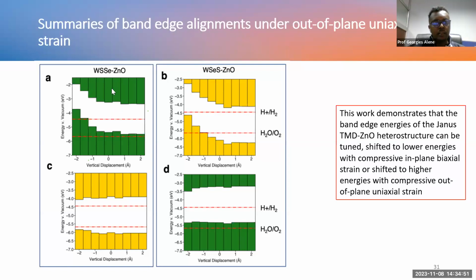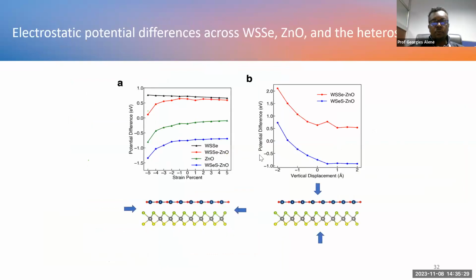For example, here the conduction band minimum is decreasing in energy when we apply tensile uniaxial strain and so on. And one interesting thing we have seen is, this heterostructure is good for overall water splitting when we see it on the S side of the heterostructure. Yeah, so we investigated this type of properties.